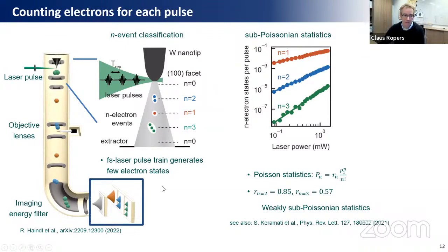And then the temporal resolution of this electron detector that we use is high enough to count the number of electrons in every laser pulse and also measure the electron energy of every electron in each laser pulse. So for example, here as a function of laser power, it's a linear emission process. This is the rate of laser pulse events which have led to the production of a single electron in a laser pulse. So these are basically one electron events, and they linearly increase basically.